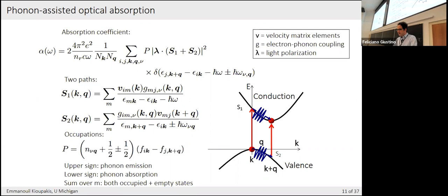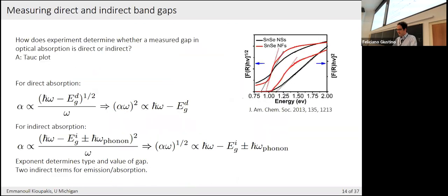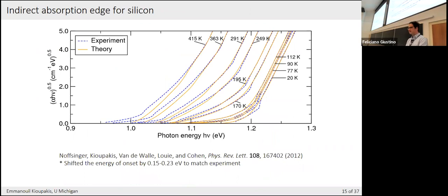Yeah, that's a good question. I think, particularly for silicon, excitonic effects may affect the spectra, but they don't change the peak position, just because excitonic effects are weak in a bulk semiconductor like silicon. We see that also in the direct spectra, where excitons change the peak amplitudes but not the peak position, usually by a factor of 2 at most for a material like silicon. I also suspect that in an indirect gap material, the excitonic effects would in general be weaker than in a direct gap material, because of the separation of the electron and the hole in momentum space. So those Coulomb matrix elements won't be as strong as in direct absorption. Of course, I won't be able to tell for sure without doing the calculation, but that's a great topic to explore.